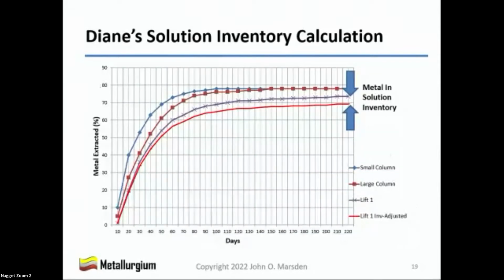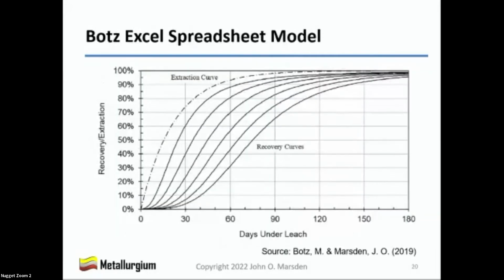Next slide. And so when you actually take into account the metal in solution inventory in a multi-lift heap, you find that there are several percent of recovery that are held locked up in solution in that heap until you eventually shut down a particular heap or move to another leach pad liner area. So you've got a number of things that are holding up gold and silver in solution. Next slide. And so she hired Mike Botz to prepare an Excel spreadsheet and develop these curves for each lift of the ore on the heap and built that into a pretty effective heap leach production model.